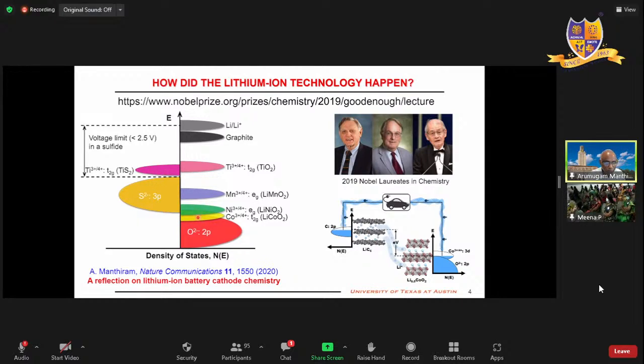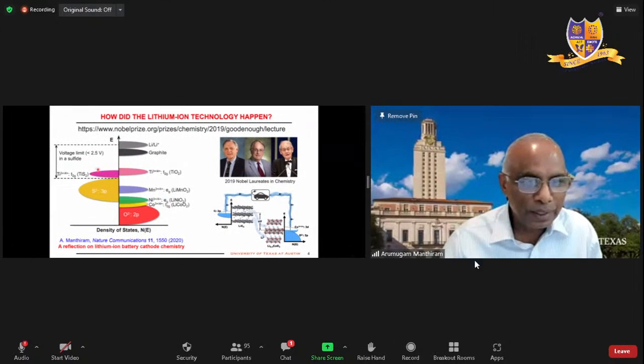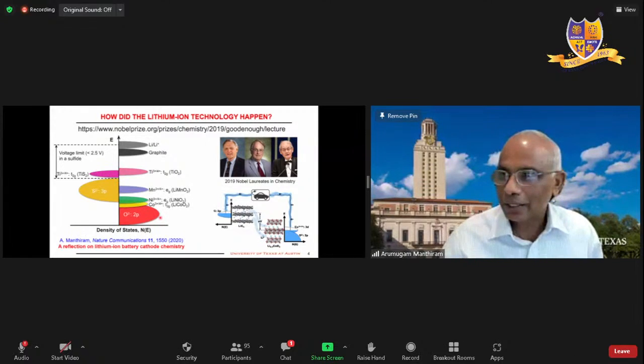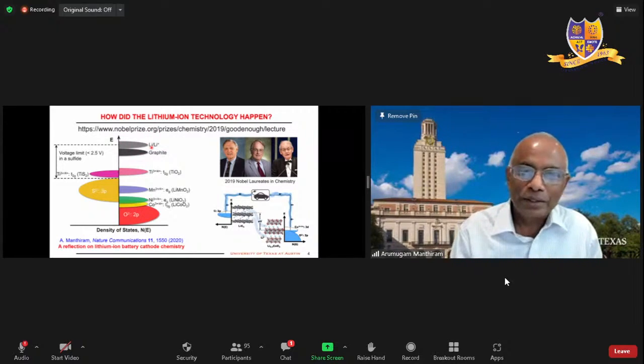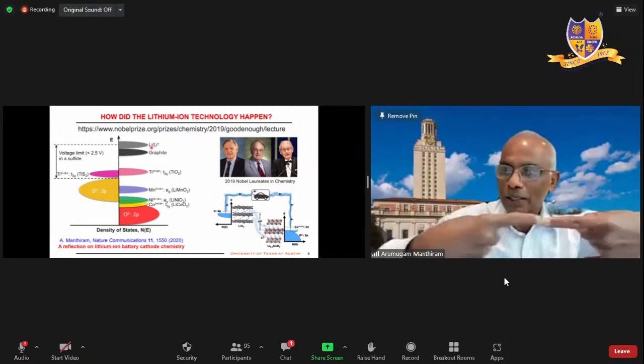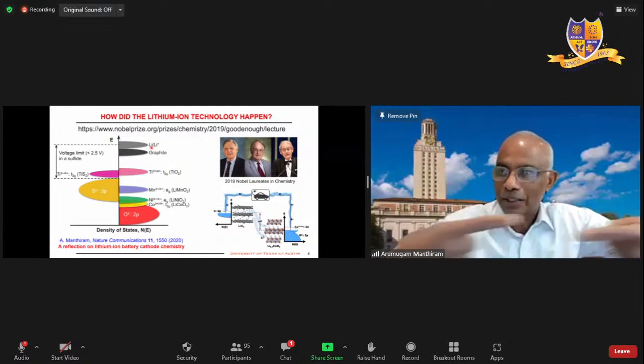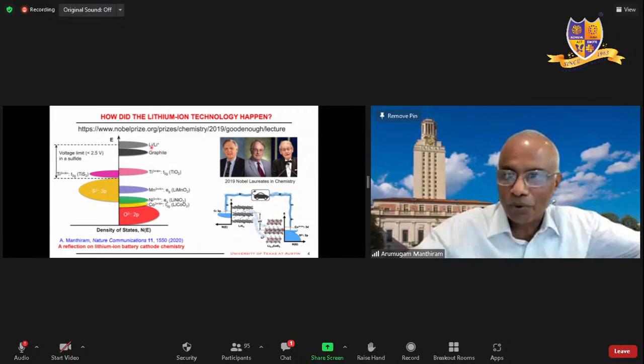I can lower my cathode energy, not somewhere here, I can go all the way down to the top of the oxygen 2p. So suddenly, the voltage could be increased by using an oxide cathode instead of a sulfide cathode, from less than 2.5 to 4 volt. Yeah, good. Energy density is increased, number one. Number two, you have a problem with lithium metal because that is forming dendrite and making a hole across the separator and connecting the anode and cathode. Therefore, you have the current flowing internally.